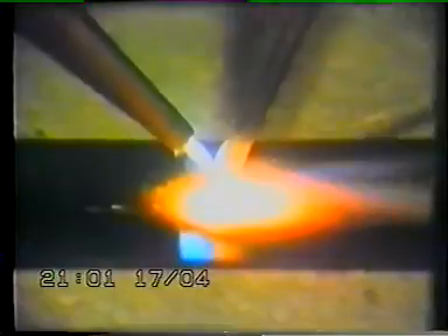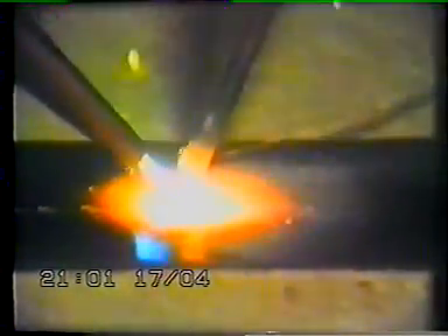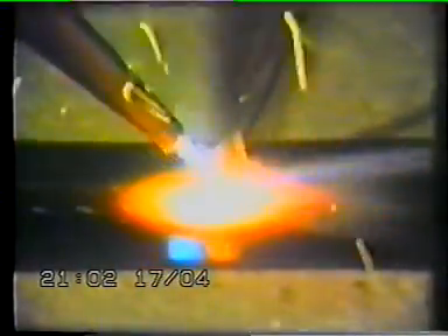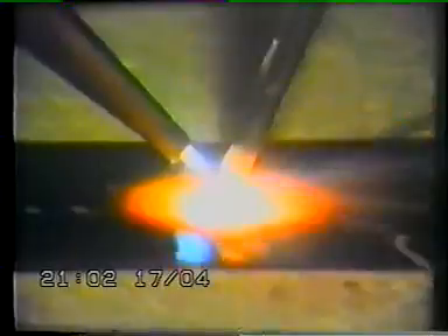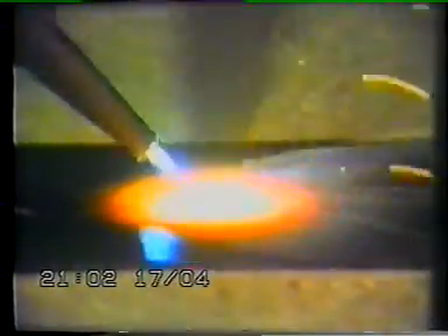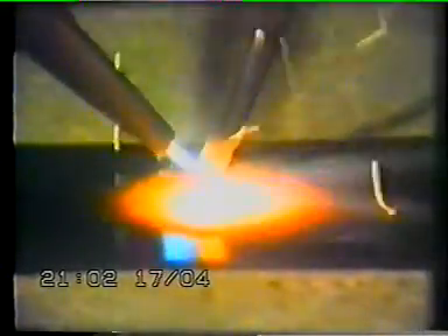The flame should be kept a proper distance away from the metal. If it is too close, small blowholes form and the torch might backfire or pop. However, if it's too far away, there won't be sufficient heat. Also, never put the torch right into the puddle. Don't hold the torch in one spot too long. Keep it in motion. The rate of travel depends on the rate of melting.